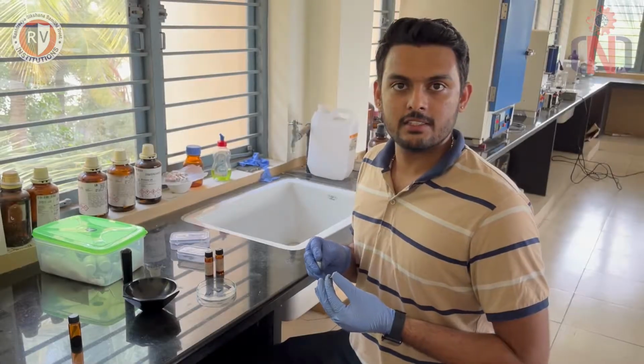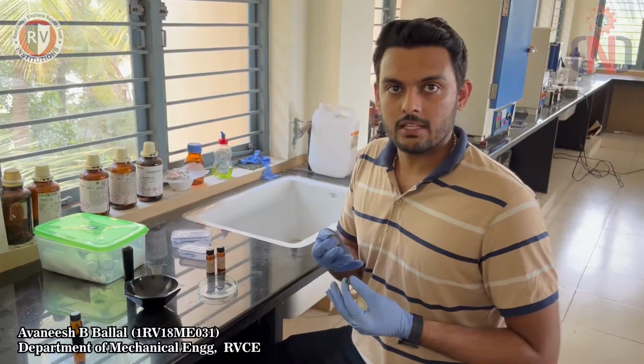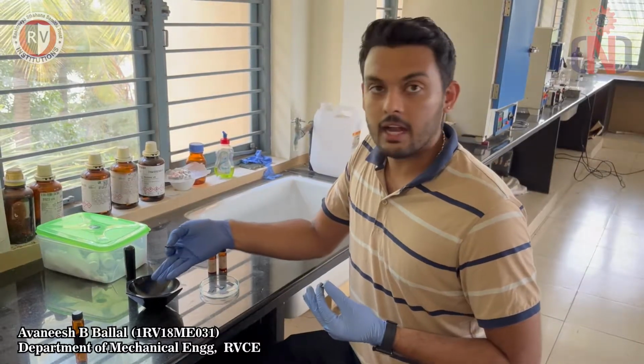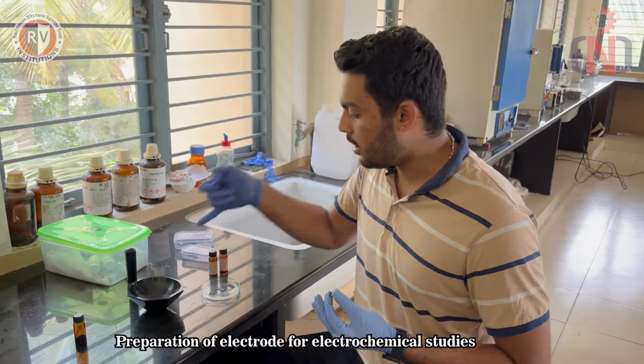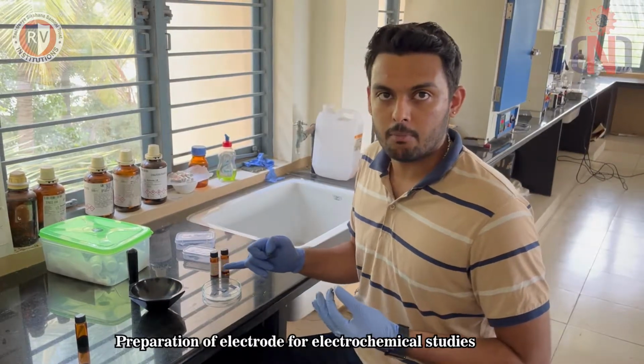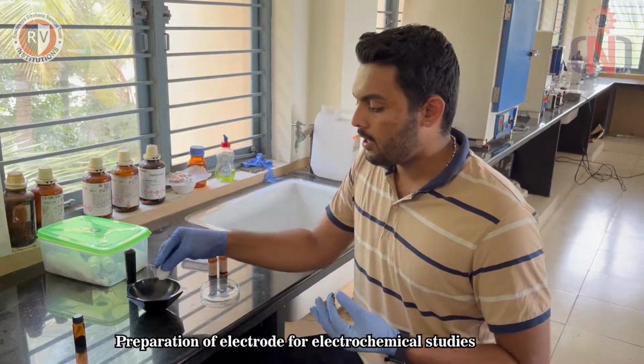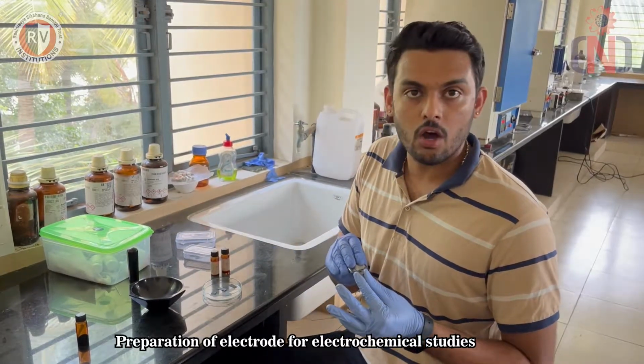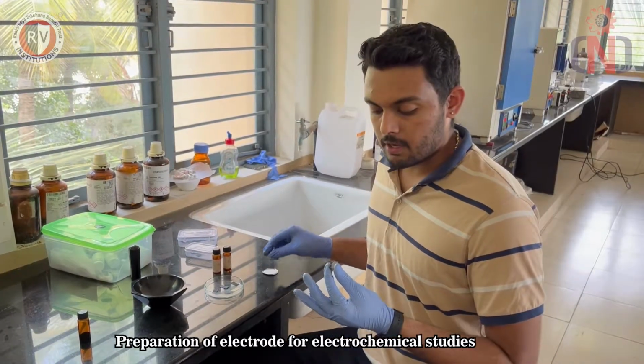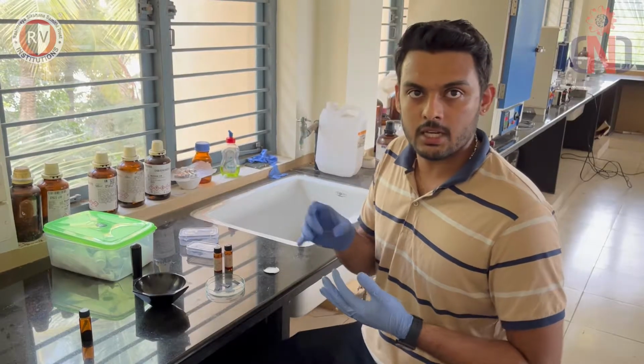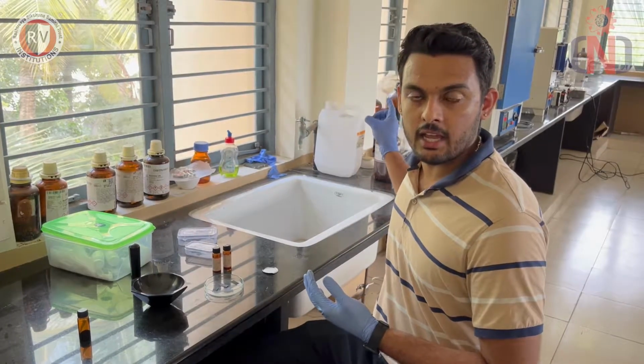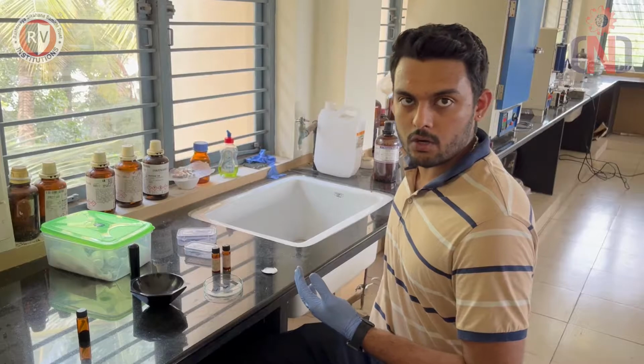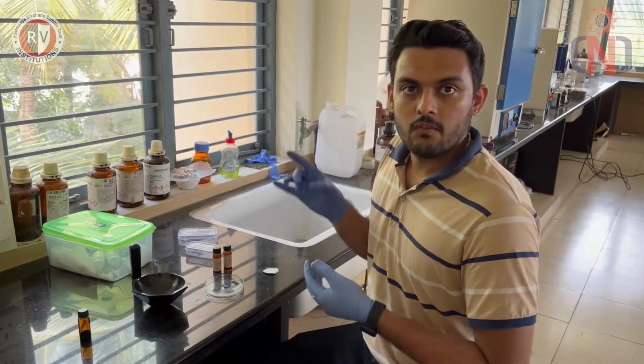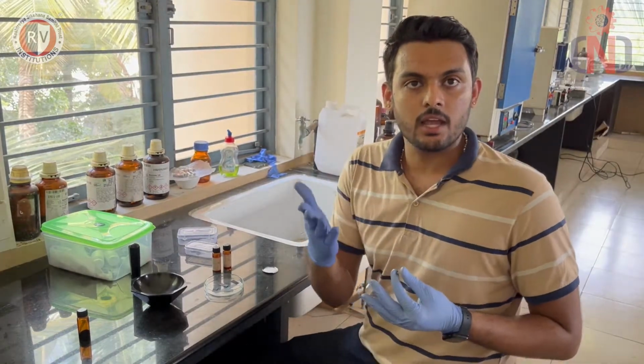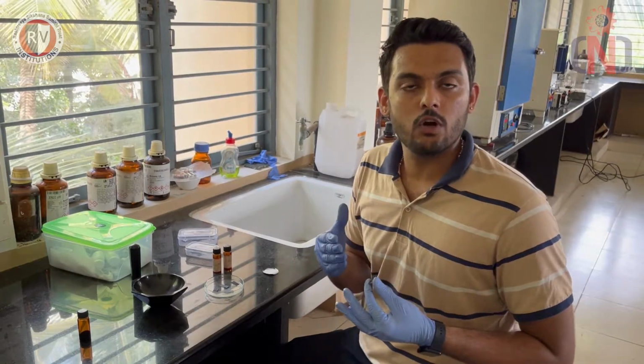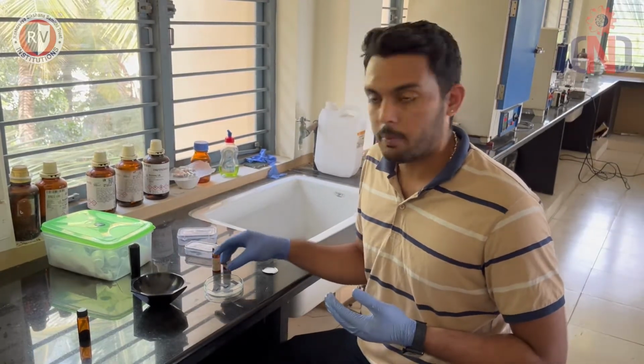Once we have synthesized the nanomaterial, we use it as a working electrode. So we put that material in a mortar, then we add PVDF and NMP. Once the slurry is prepared, we remove that material and paste it on a Toray carbon sheet. Once pasted, it is kept for drying at 80 degrees Celsius for 2 hours. Once it's dried, we use that as a working electrode to check cyclic voltammetry and chronopotentiometry for supercapacitor application.